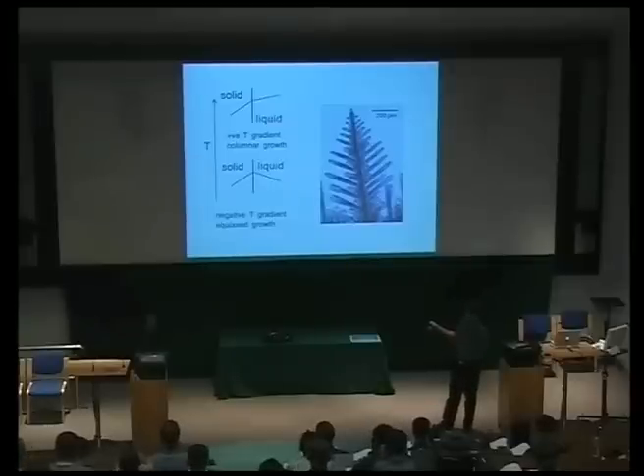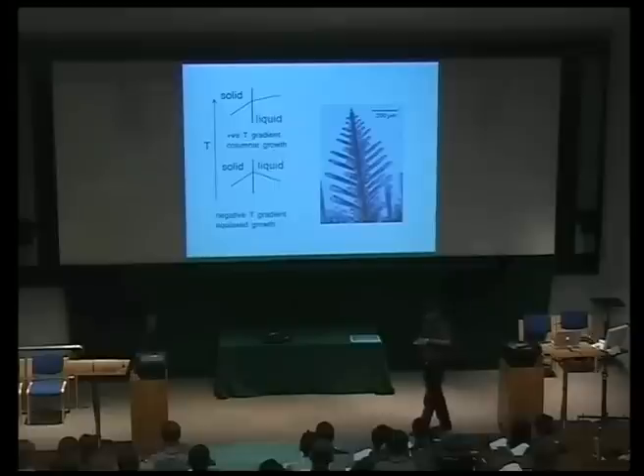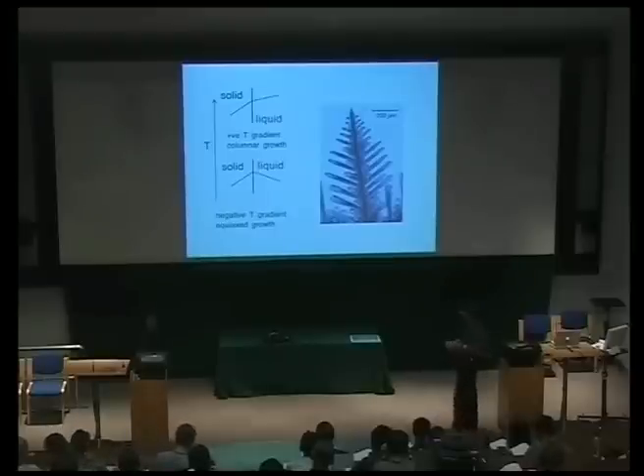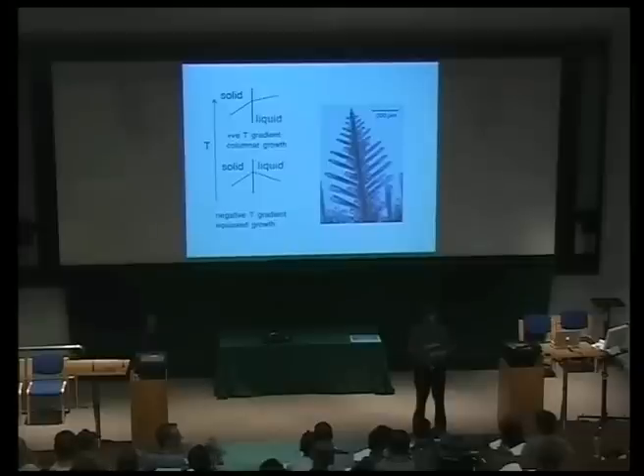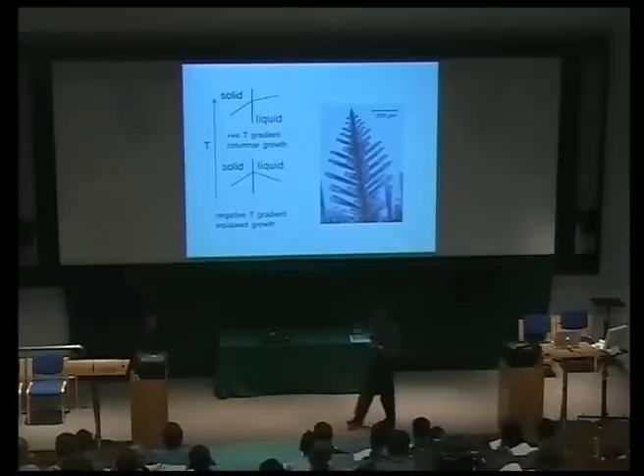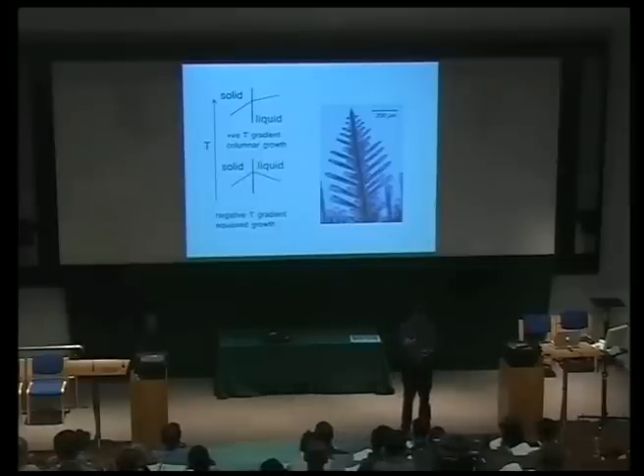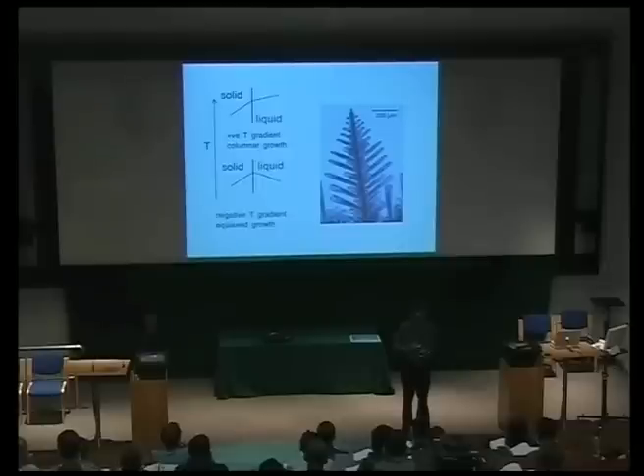This kind of scenario is actually quite rare — where you get a negative temperature gradient in the liquid. One example is if there is a lot of latent heat of fusion evolving at the interface, giving a higher temperature at the interface than further away in the liquid. And yet when we look at solidification, we see dendrites everywhere, even in impure materials and even when there is a positive temperature gradient in the liquid. The particular supercooling we'll discover today is because of solute concentration gradients, and that's why it's known as constitutional supercooling.